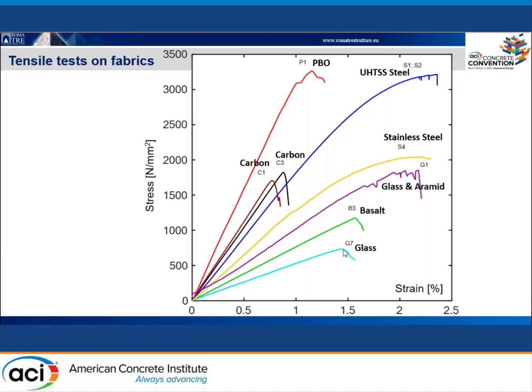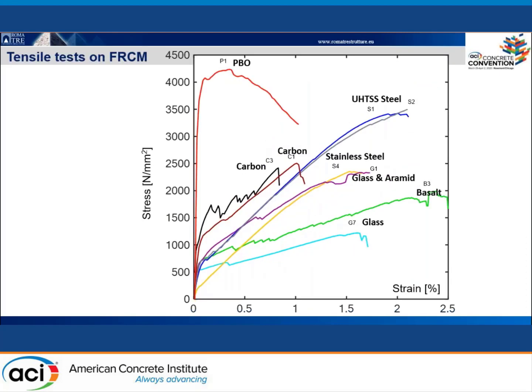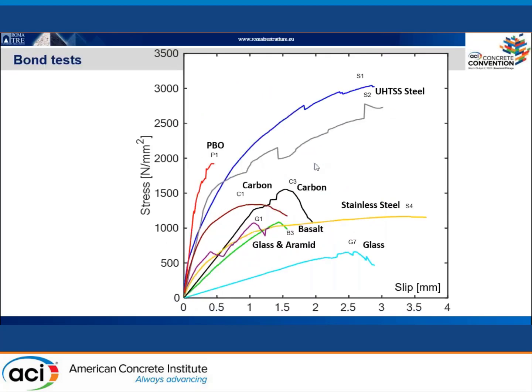Things change a little bit when passing from textile to FRCM specimen, because here you have the contribution of the matrix, and this explains why you have this first branch, which is much stiffer before the matrix experiences some cracking, while after cracking the behavior is quite similar to the bare textile with some tension stiffening. And things change again when passing to the bond behavior, because the bond behavior is very different. If you look at the PBO, the tensile strength was more than 4000 megapascal, while the PBO bond strength is lower than 2000 megapascal. And the same happens for carbon systems and also for stainless steel systems that experience some slippage.